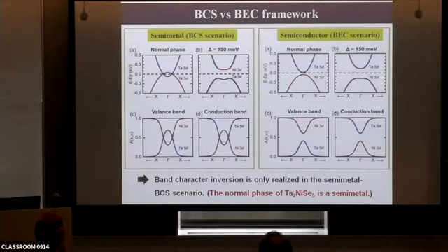Okay, so even if we consider the band hybridization in the normal phase, it cannot explain the huge energy gap observed in the STS data. Therefore, in order to explain the energy gap observed in the STS measurement, we need to introduce the interband interaction in the normal phase. So you're saying a single particle hybridization is just too small? Yeah. These hybridization numbers were not too large. Okay. Andy? So two questions.